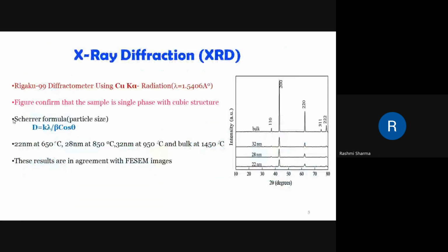So here, this is the X-ray diffraction pattern found for different sizes. What the X-ray diffraction pattern describes is that from it we can determine the size of the particles. To get this X-ray diffraction pattern, copper K alpha radiation was used, and the wavelength of the radiation was 1.5406 angstrom. This pattern is obtained by using an instrument called the Rigaku diffractometer. We use this pattern to find the size of the particles.